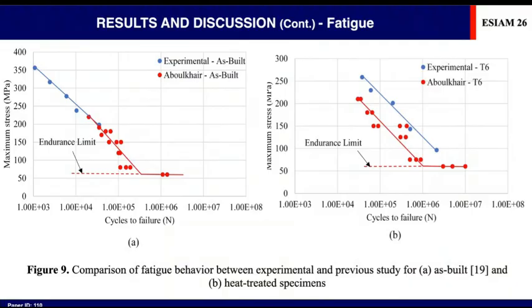In comparison to the as-built specimen, the heat-treated specimen shows a similar number of cycles across the stress range. It shows favorable fatigue behavior in the low stress range, with no run-out during the test, even when performed at the maximum stress. At stress more than 200 megapascal, the fatigue life is limited to the low cycle regime. The T6 specimen shows longer fatigue life at a comparable stress level. The residual stress is reduced and the grain stabilization improves homogeneity and also reduces scatter. Therefore, the T6 treatment significantly enhanced the fatigue resistance.